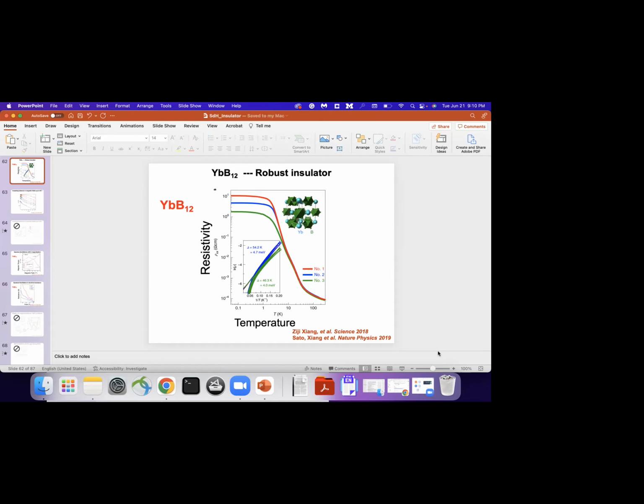I have a question. So from the theoretical perspective, this ytterbium boron, is it also a topological Kondo insulator? That's an excellent question. This is a very interesting question. Indeed it is, in the sense that the early prediction or early band structure calculations eventually show the gap opening, and they argue that it's not exactly time reversal symmetry protected, but protected by the crystalline symmetry. In other words, they believe this is a topological crystalline insulator. That's from the theoretical prediction. On the experimental side, photoemission actually identified the surface state with an odd number of Fermi surfaces, which actually supports that this is an actual topological insulator at zero field.